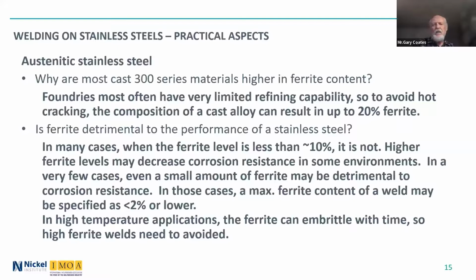In high temperature applications, ferrite can embrittle with time. It can become brittle. If you have a small amount of ferrite in an alloy, you have a series of hard particles. That generally is not a problem. It actually makes the material a bit stronger. But where you have high ferrite welds, 10% or higher, you can lead to cracking in service. Now, all that takes time, so you don't see it right away. It might take a year or two before it actually fails.